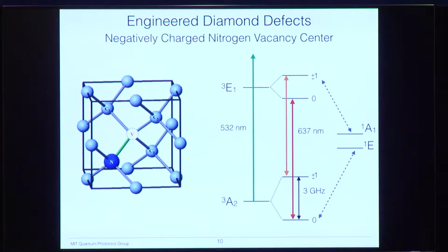On the right here, we see a simplified level diagram of this NV Center. We save the information in these ground state levels that are split even at zero field by around 3 gigahertz, and we can split out the plus and minus 1 states with the application of a B field. And we also have these optical transitions. This is in red, around 637 nanometers, and we'll use that to create entanglement between remote NV centers. And then finally, we can also excite above band with green, or 532 nanometers.